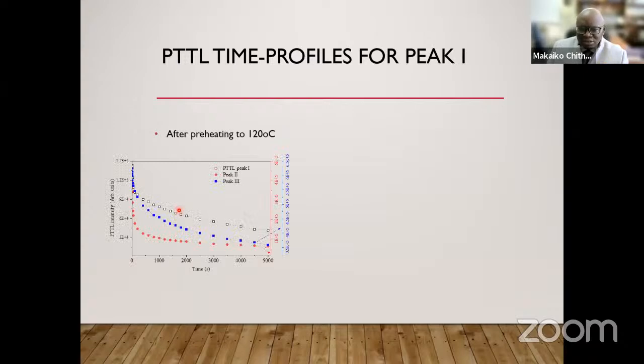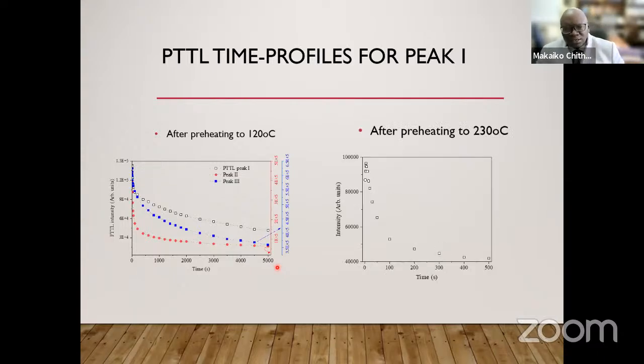So here are experimental results. You have PTTL intensity versus duration of illumination. And we can see that peak 1 simply decreases, as does peak 2. The intensity of peak 3 goes up a little bit, then continues to decrease. And this is measured over 5,000 seconds. Once you have removed peak 2, we can see that the intensity of peak 1 goes up a little bit, then decreases. The number of donors for peak 1 here is 2, and the number of donors here is just 1, since peak 2 is removed. Again, let me emphasize that these are qualitative conclusions.